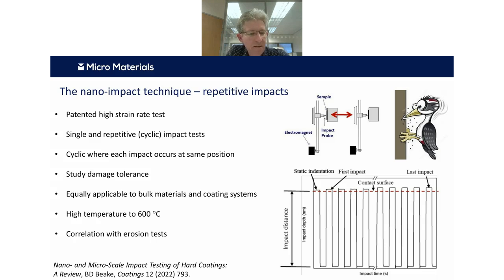So instead of these single impacts, we can repeat that process. So now, instead of milliseconds, we're combining repetitive tests, typically, as I say, at the same position. And then effectively we've got a surface fatigue test. And this allows us to look at the number of cycles to failure and really start to understand the damage tolerance of these typically coating systems, but also bulk materials. And we can run these tests at room temperature, or we can run them at high temperature as well. And in practice, they correlate very well with erosion tests.